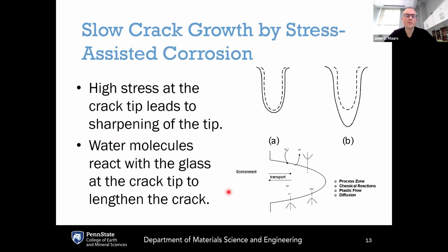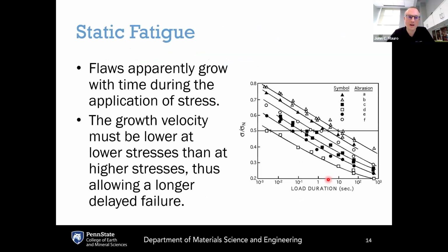A few other things we need to keep in mind for the mechanical properties of glasses, especially under many years of operation, is stress-assisted corrosion or slow crack growth. For silicate glasses, this is governed by interaction between water molecules from the environment and the crack tip itself. Water molecules can come in from rain or humidity in the environment. They come into the tip of the crack, which is under stress, and react with the silicate molecules at the crack tip. When a water molecule interacts with silica, it breaks one of the bonds and the crack becomes one molecular unit longer. Over time, water can propagate to the crack tips, react, and continue to make the cracks longer. This will compromise the strength of glass products.